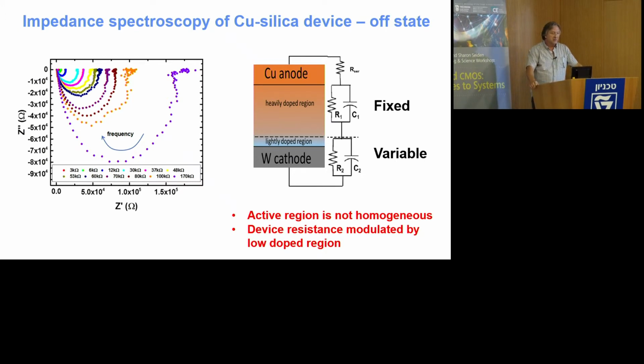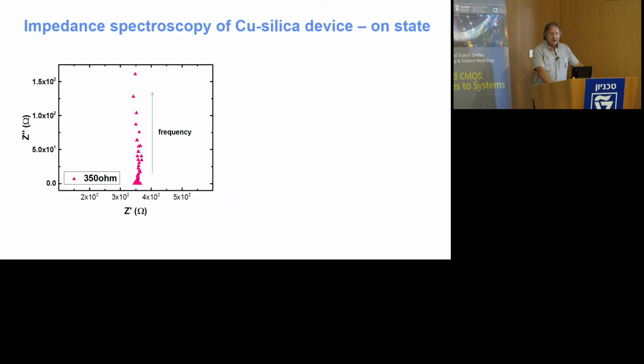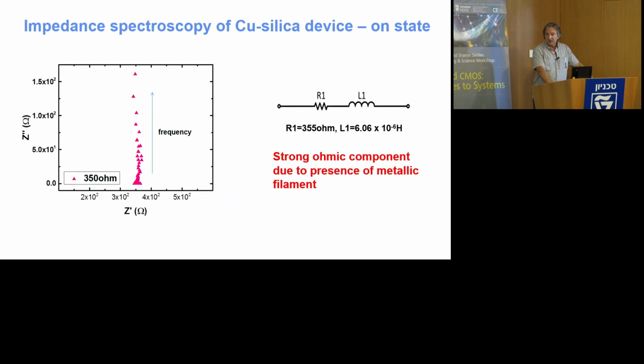And it explains as well why these things can be quite fast, even when you have relatively thick oxides involved, 100 nanometers or thereabouts. On state, no big surprise there. It is metallic. It is a copper filament, and you can see that again by impedance spectroscopy. When you get to the few k ohm on-state resistance, above there in the intermediate range, we have a number of interesting things going on at the moment.